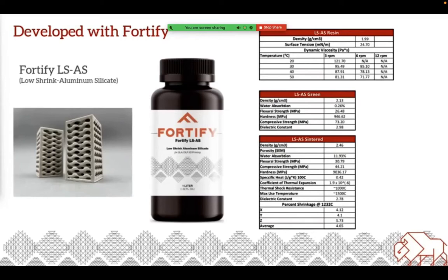So, what applications is this LSAS material good for? While ceramics don't have great tensile strength, they are very strong in compressive strength. If you have an application that needs to withstand temperatures between 300 C and 1300 C, this material won't flinch at all. While not fully dense, this material can be used for a lot of applications in the oil and gas, electronics, and automotive industries.